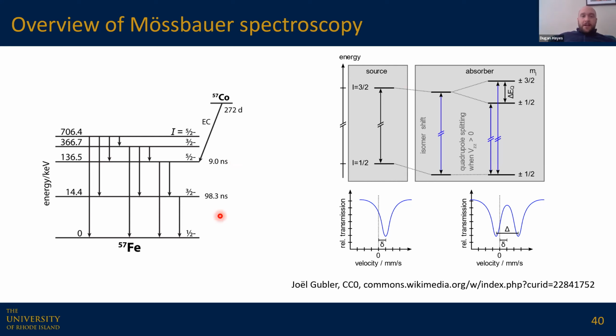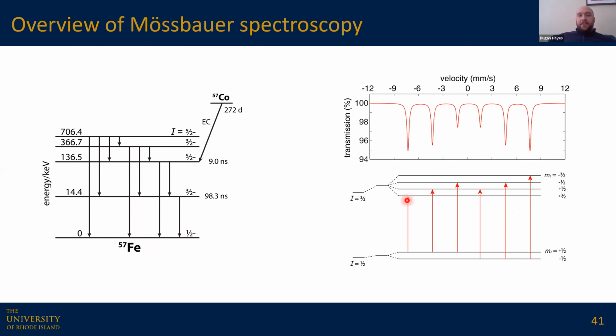So just a quick overview for the case of iron, which is by far the most studied Mossbauer nucleus, iron 57, we're probing this 14.4 keV nuclear transition. And you typically do it with a cobalt 57 radioisotope source. You're able to get these 3 parameters: the isomer shift, the quadrupole splitting, and the magnetic hyperfine splitting. You can correlate that to spin, oxidation state, ligand geometry, covalency, things like that, and learn about the chemical environment by doing a nuclear spectroscopy, not an electronic spectroscopy, although it's reporting back on the electronic environment. You have these very narrow line widths due to the long lifetime of this excited state.